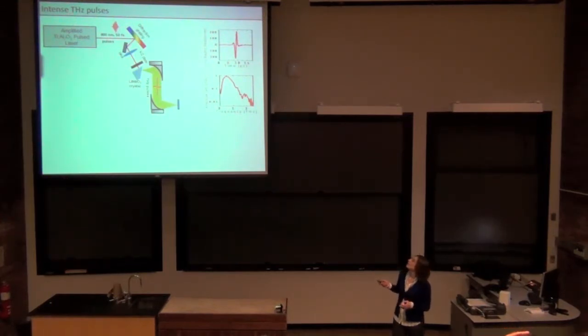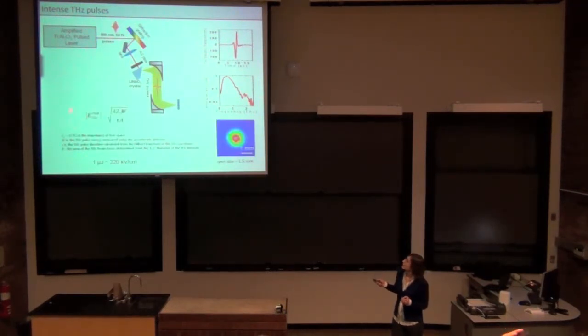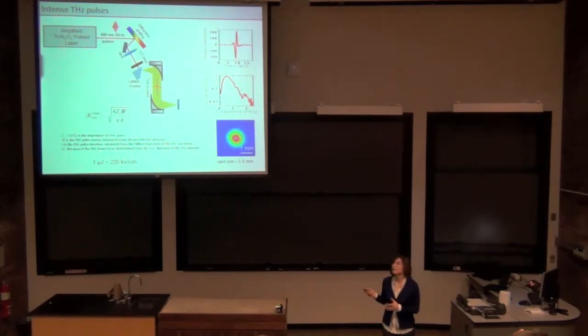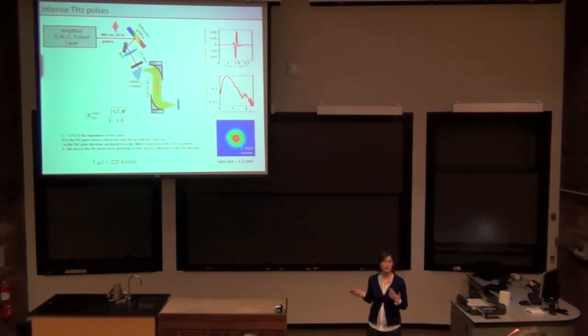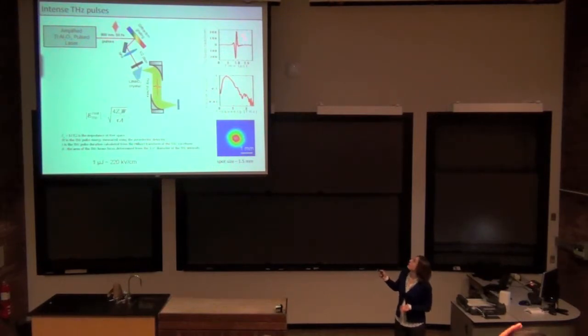To make this meaningful, at 1 microjoule you can calculate the peak electric field, and what you end up having is over 200 kilovolt per centimeter. That is quite high in electric field. Right now we actually increase it even further, we increase the energy to 4 microjoules, increasing the electric field by a factor of 2. So this is the waveform that we're getting.